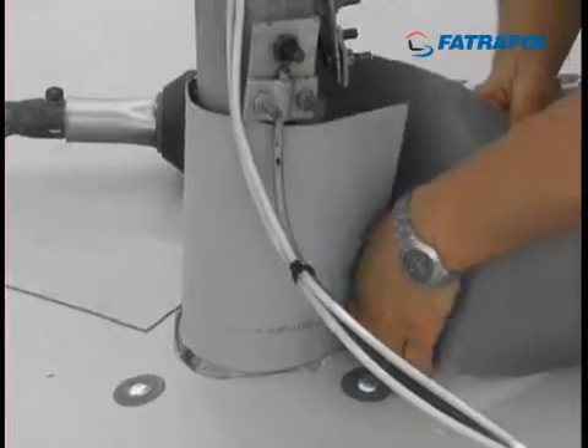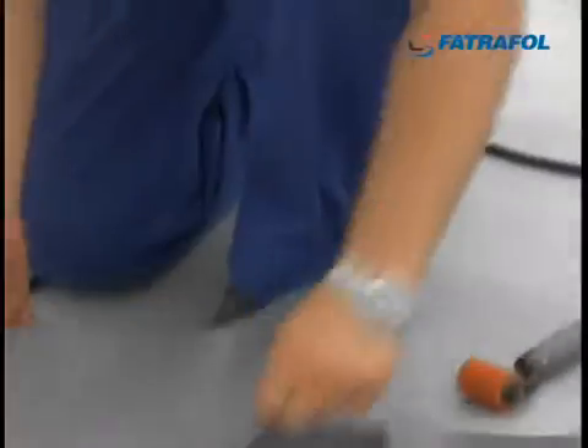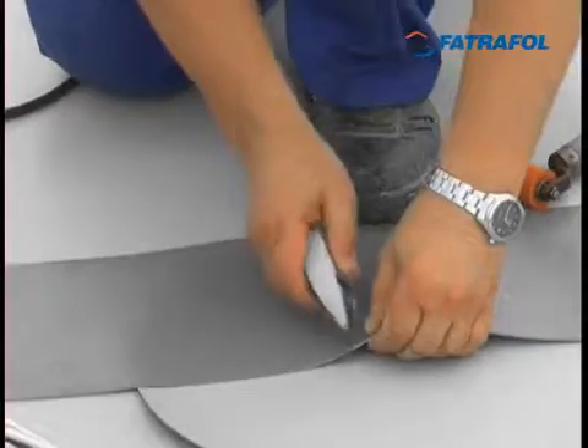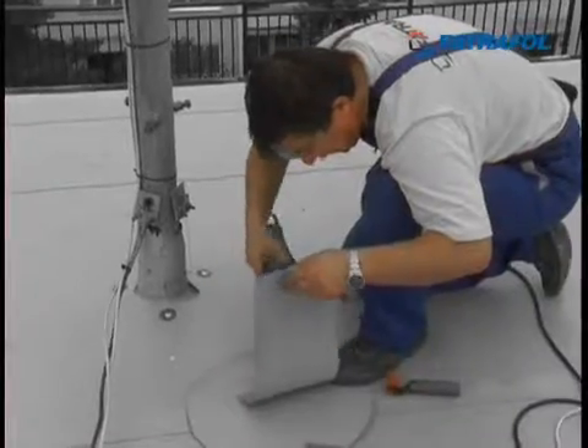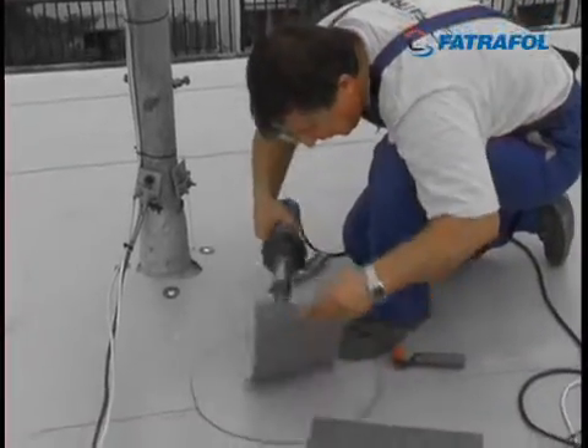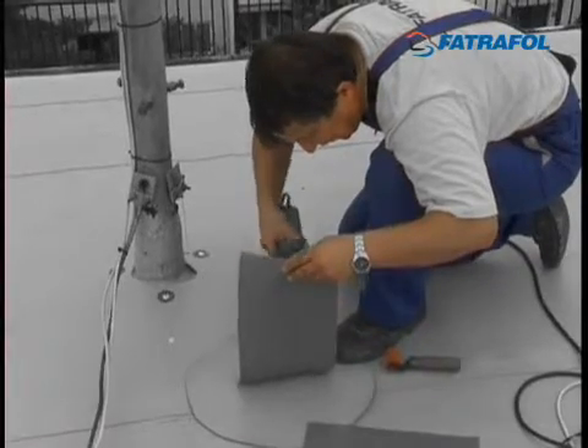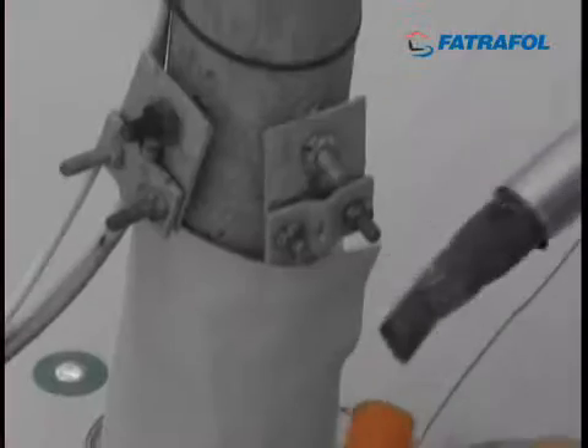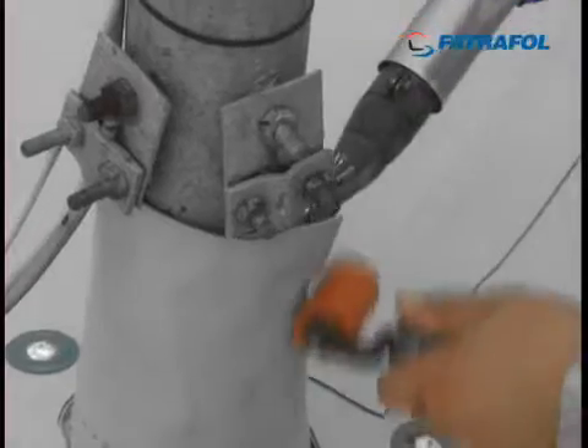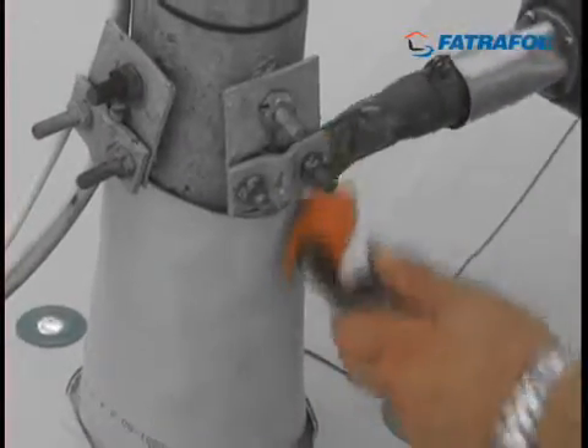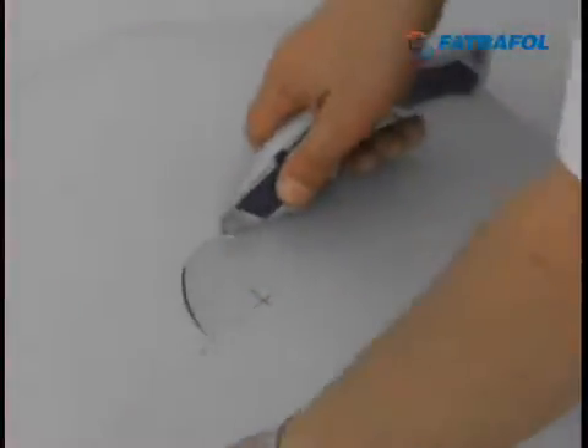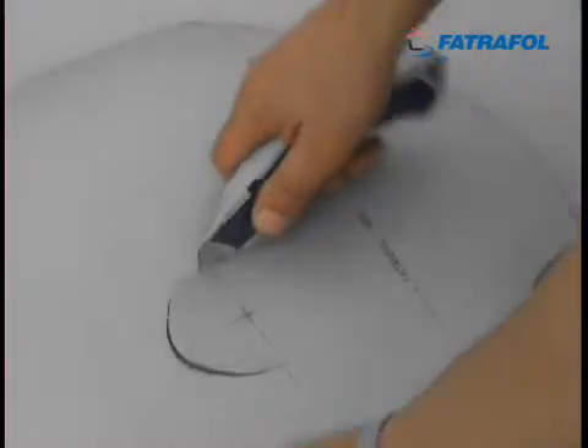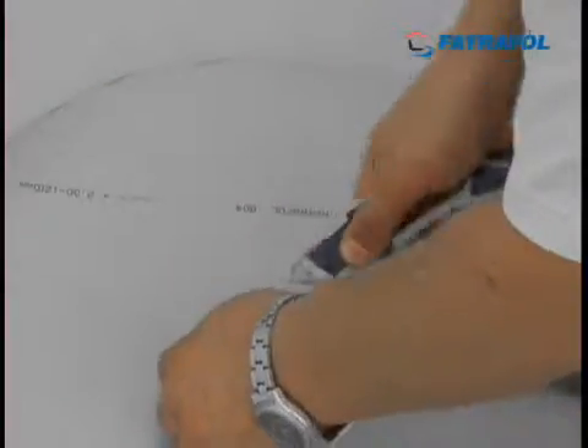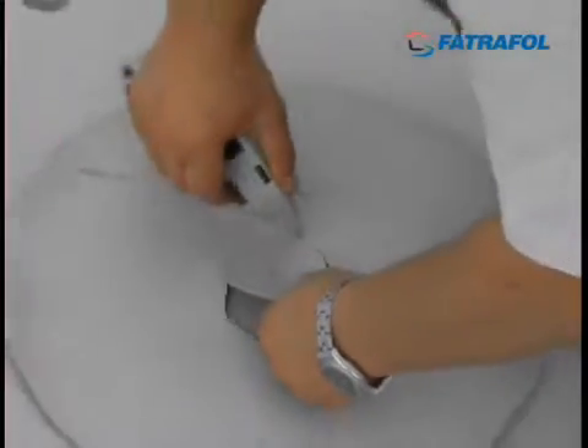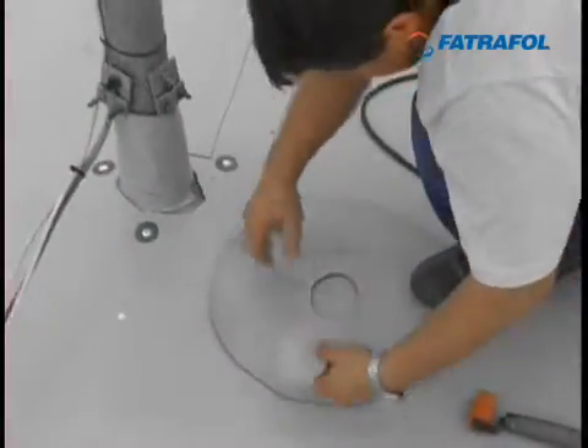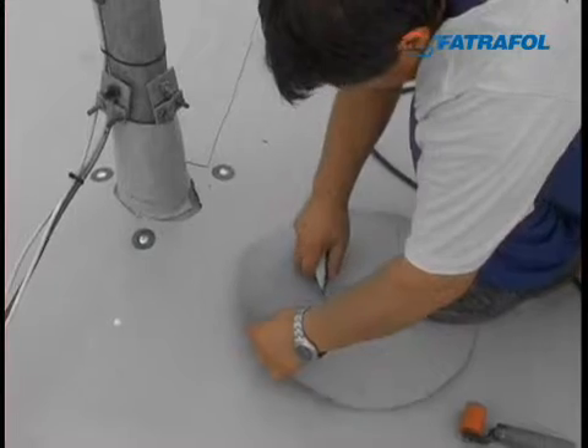At the same time, prepare a shaped component to finish the mast bottom and cut it as required. Heat both sides of the shaped component with hot air for better elasticity. Fit the shaped component tightly to the mast bottom. Once cooled and contracted, the membrane will fit perfectly around the mast. The membrane height must be at least 150 mm above the adjacent roof plane.